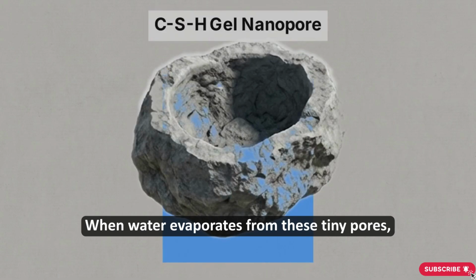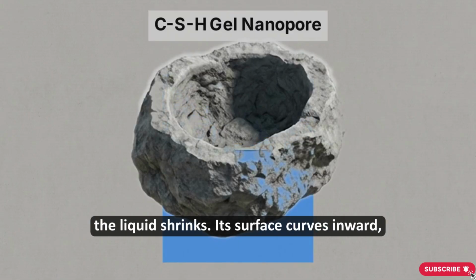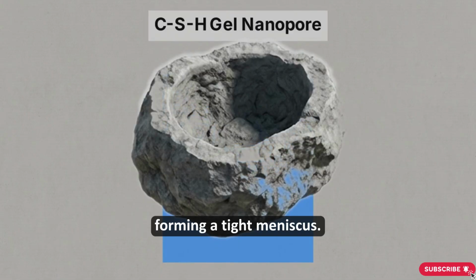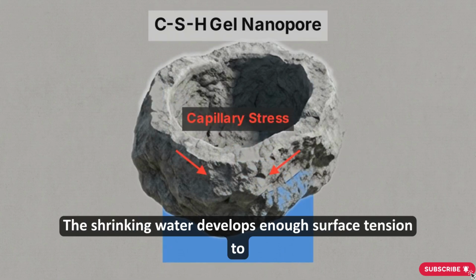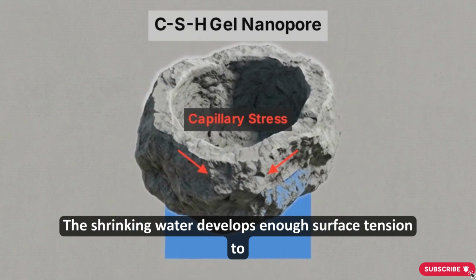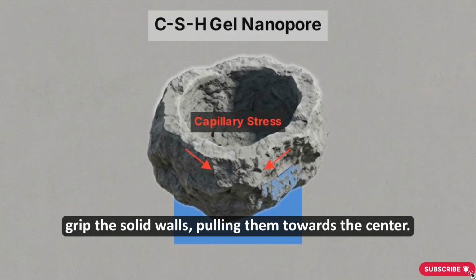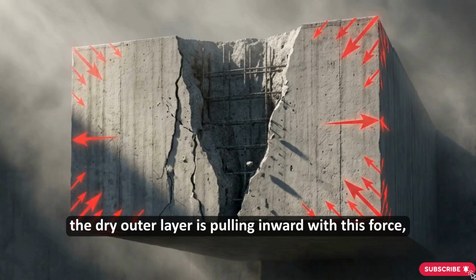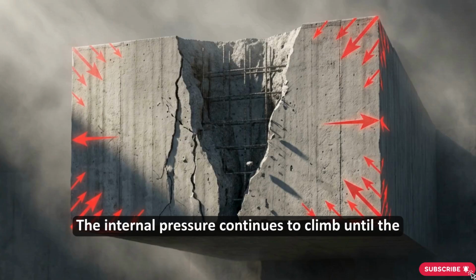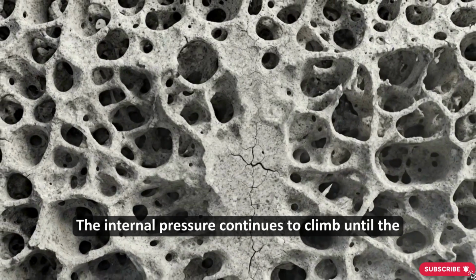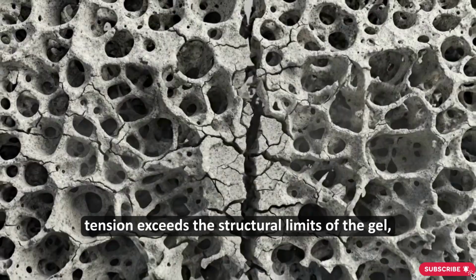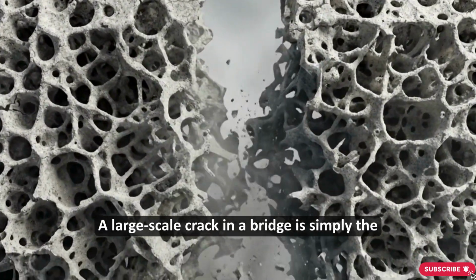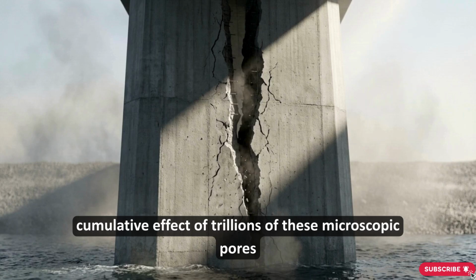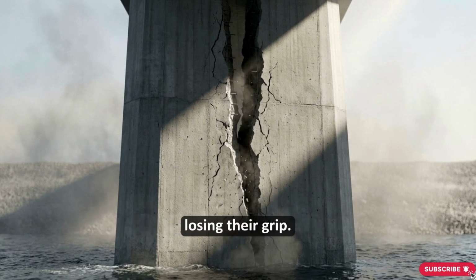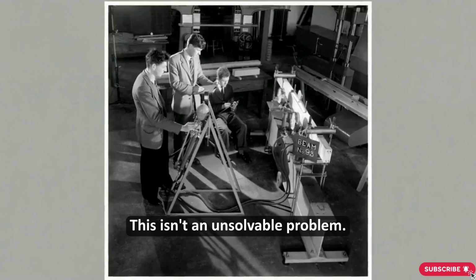When water evaporates from these tiny pores, the liquid shrinks. Its surface curves inward, forming a tight meniscus. This creates capillary stress. The shrinking water develops enough surface tension to grip the solid walls, pulling them towards the center. Across the entire structure, the dry outer layer is pulling inward with this force, while the wet inner core stays stationary. The internal pressure continues to climb until the tension exceeds the structural limits of the gel, and the binder snaps. A large-scale crack in a bridge is simply the cumulative effect of trillions of these microscopic pores losing their grip. This isn't an unsolvable problem.